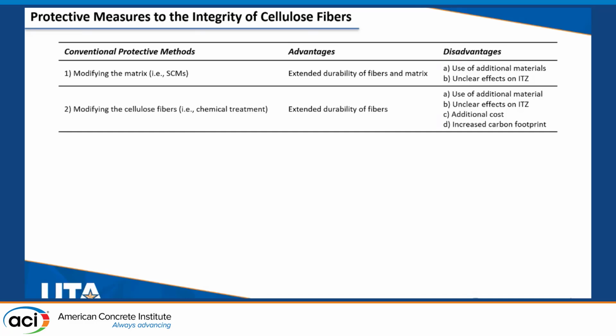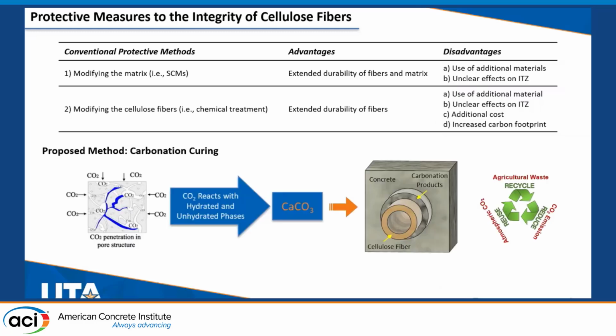The conventional protective measures include using supplementary cementitious materials to modify the matrix, or modifying the cellulose fibers themselves through different chemical treatment procedures. Although both of these methods are effective in enhancing the durability of the fibers, there are some disadvantages. Most specifically, the loss in the interfacial adhesion occurs at the later ages, so the effect of these methods on the interfacial adhesion is not very clear to us. Instead, our focus turned to the exploration of carbonation curing, which is an environmentally beneficial approach that repurposes carbon dioxide.